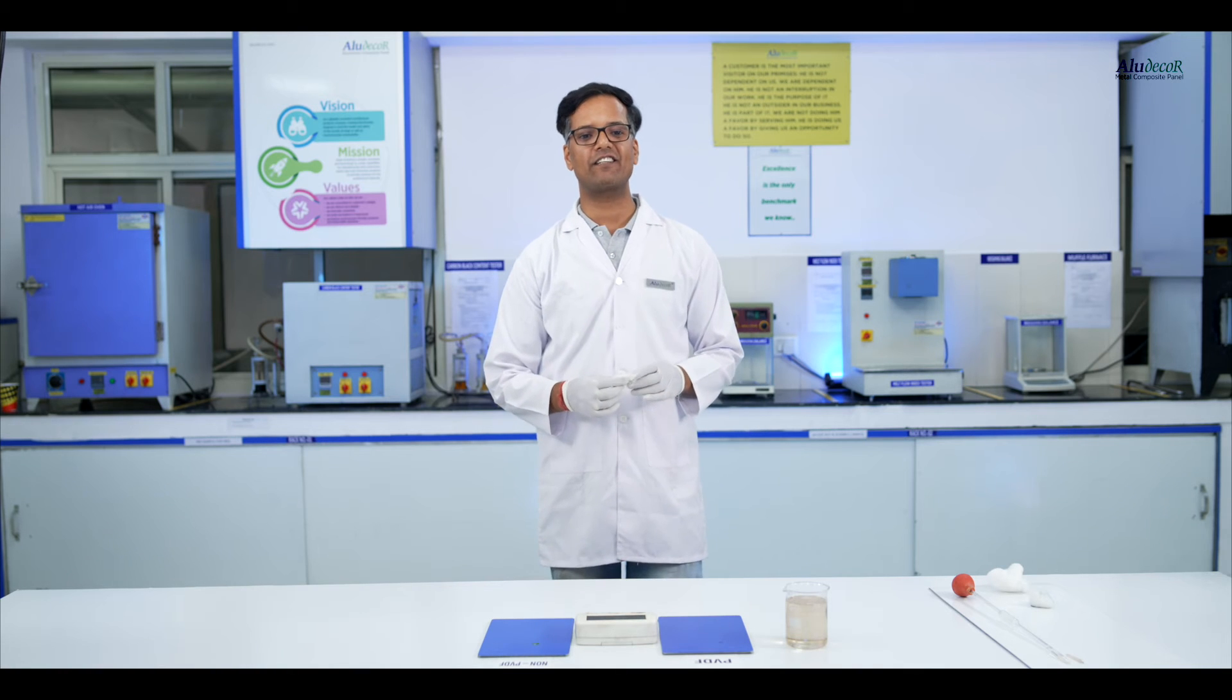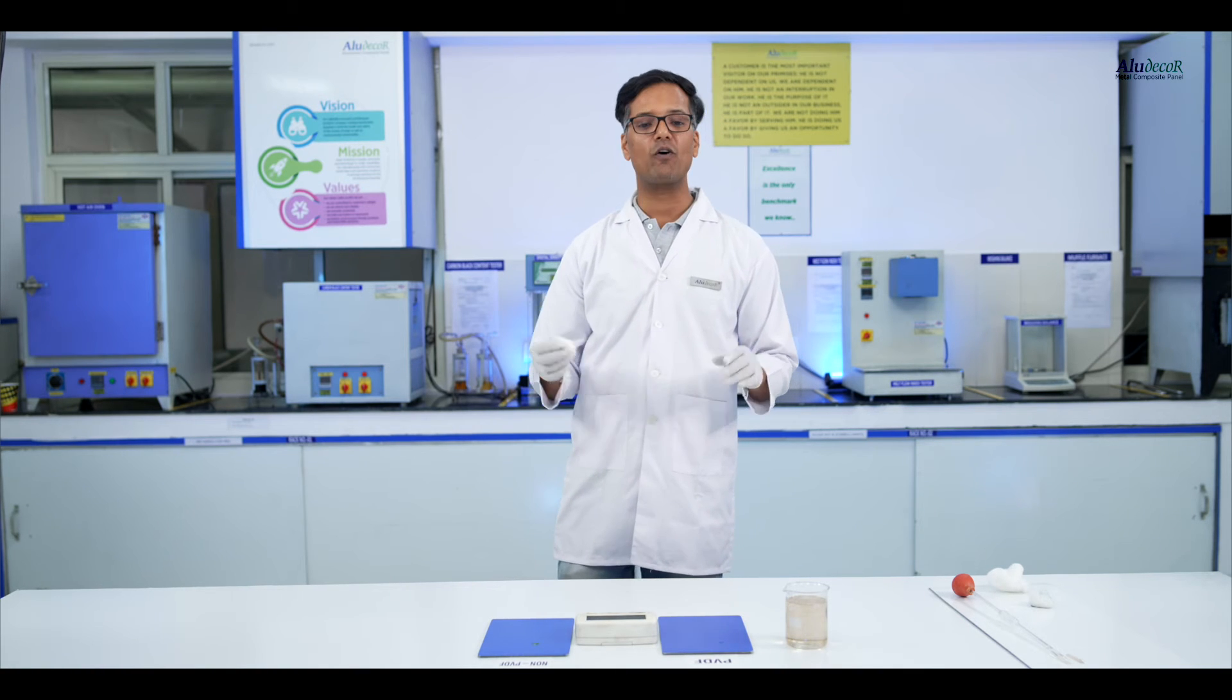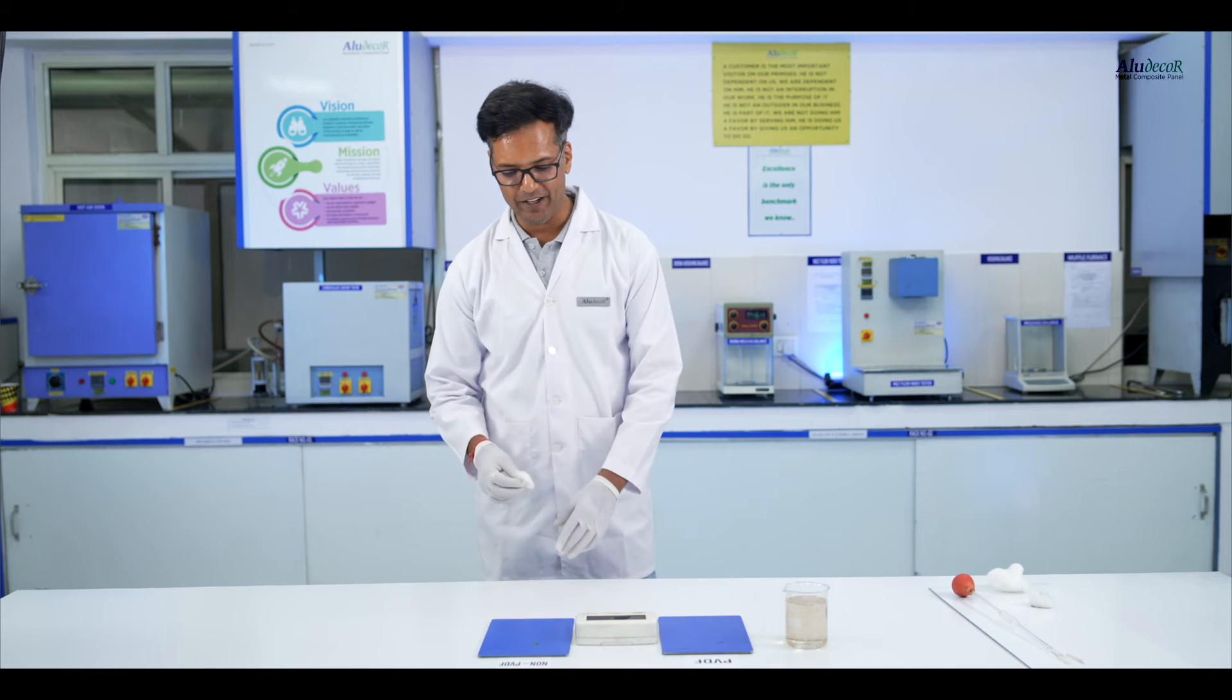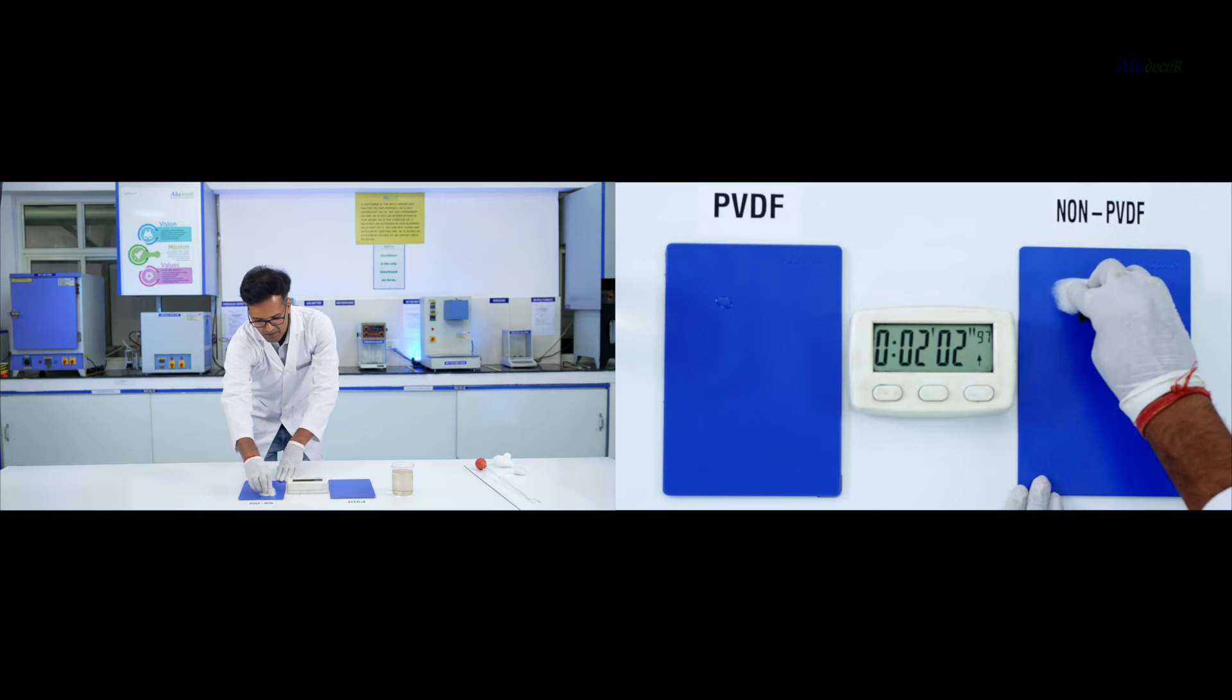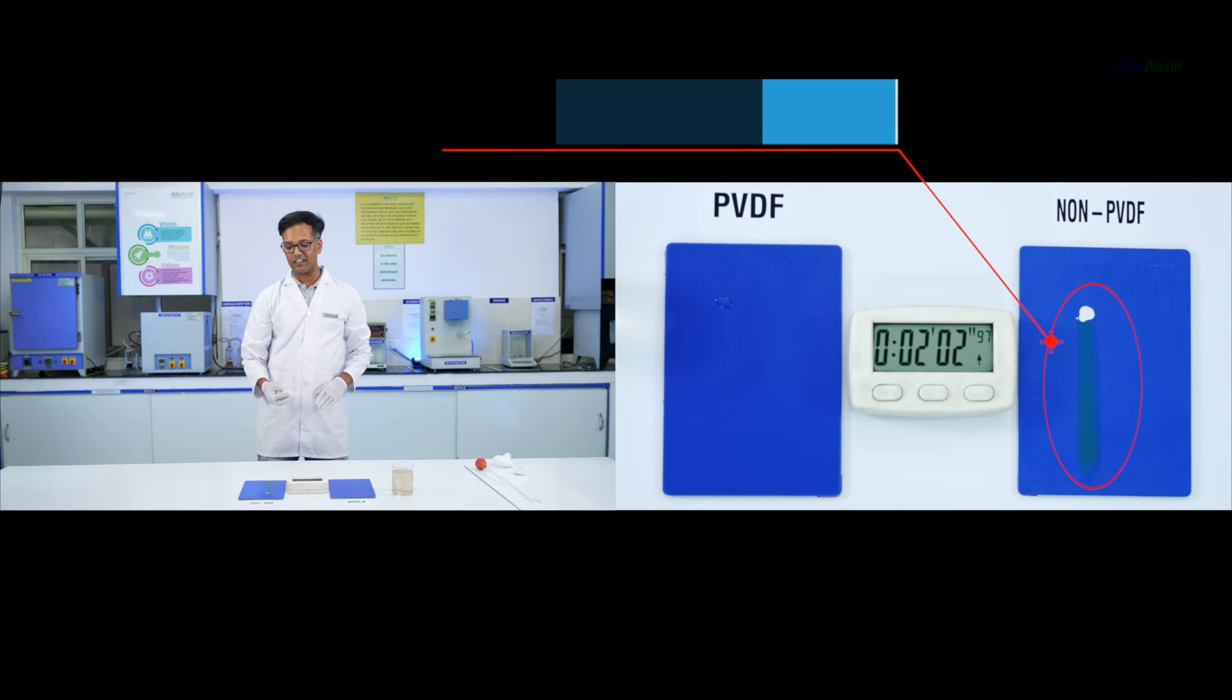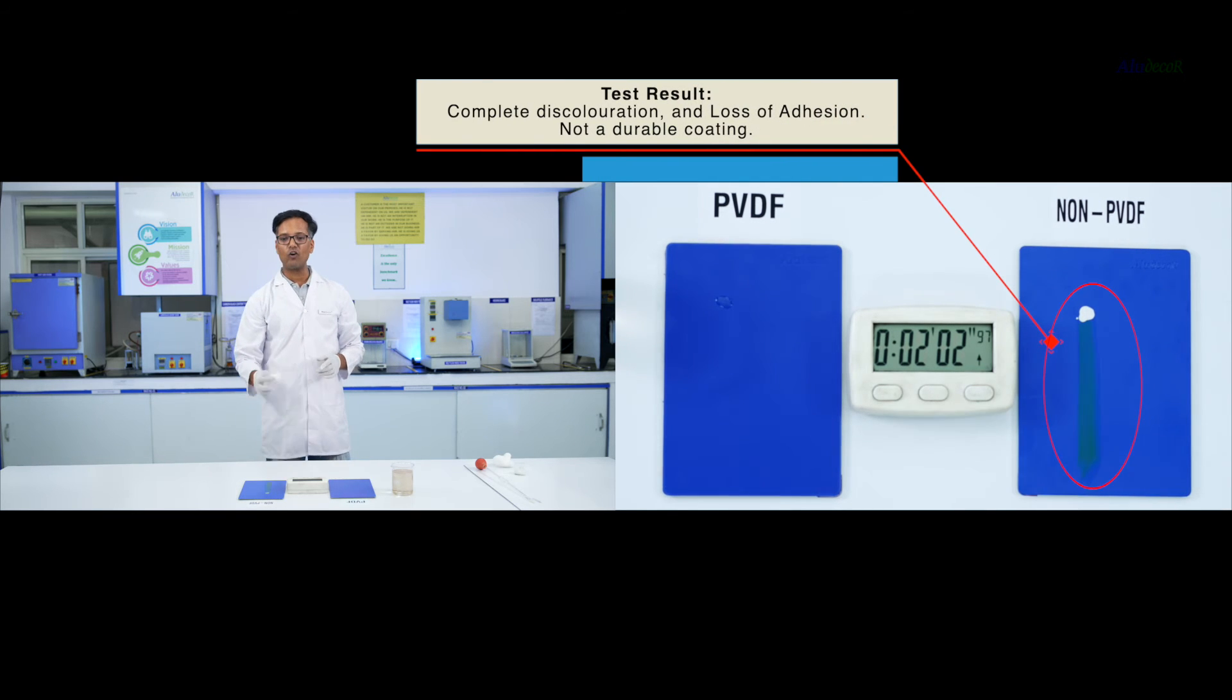Let's check out the changes. So we clean both samples. First we clean the non-PVDF sample. Oh my god, discoloration and loss of adhesion are clearly visible in the non-PVDF sample.